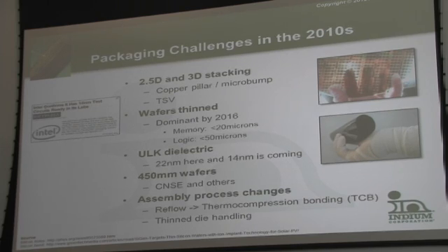There's a lot of copper interconnects within these. And these interconnects are actually embedded within a very thin layer of what's called ULK dielectric, an ultra-low K, low-loss dielectric. As these devices get smaller and smaller, the dielectric has to go down. The problem with that is that this stuff is very fragile. It's very, very easily broken.